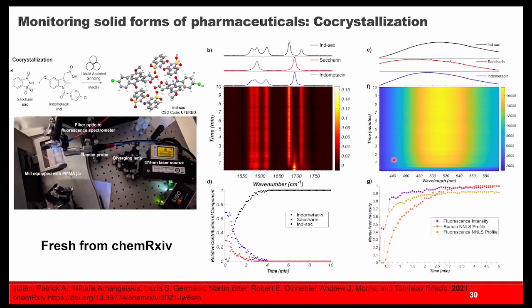And in this case, we were trying to use fluorescence to monitor this transformation because indomethacin is fluorescent in the solid state. It's extremely poorly fluorescent in solution, but this co-crystal is actually quite fluorescent. And we're actually able to monitor this reaction using fluorescence as well as Raman at the same time. And if we line up the fits that we get, we're seeing reasonably good agreement, depending on how you process the data, between the fluorescence profiles as well as the Raman.